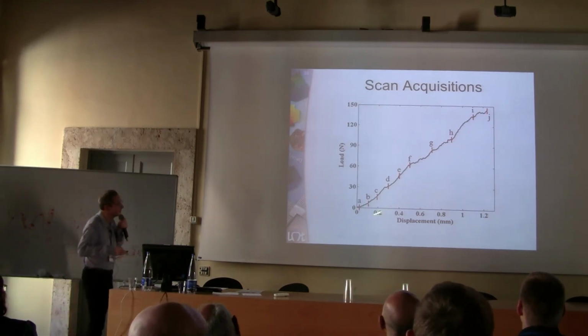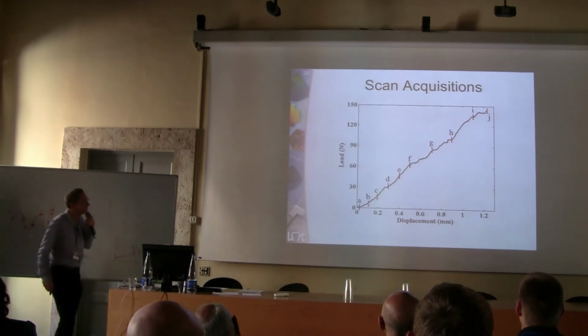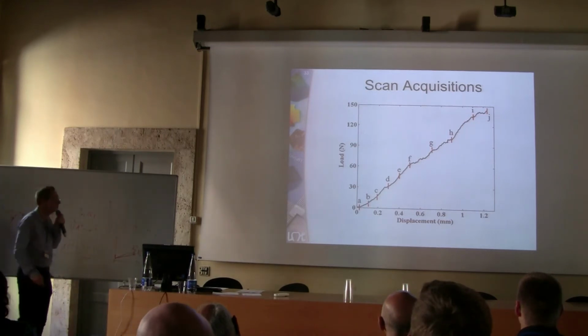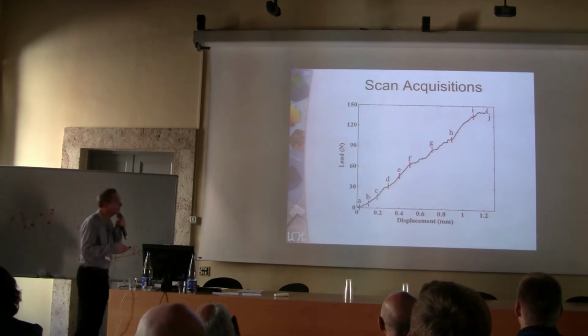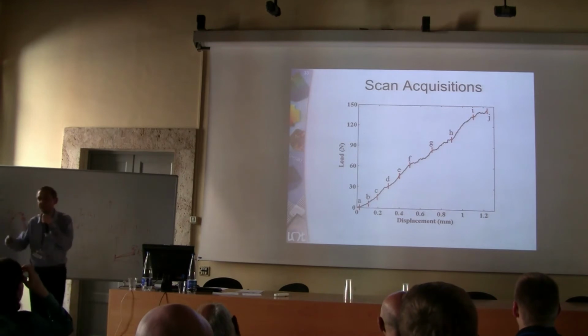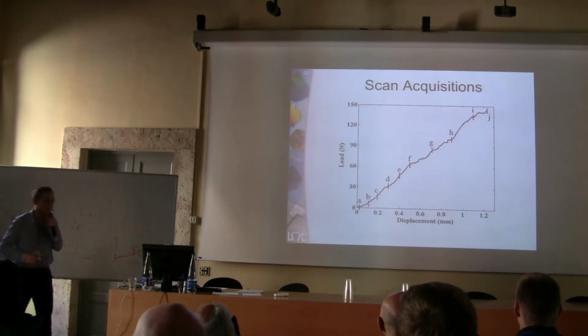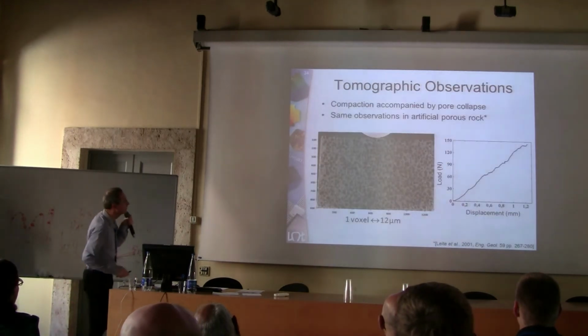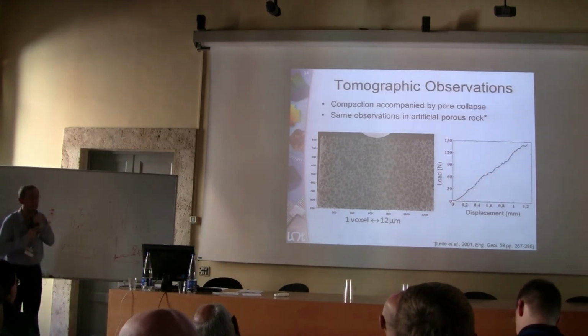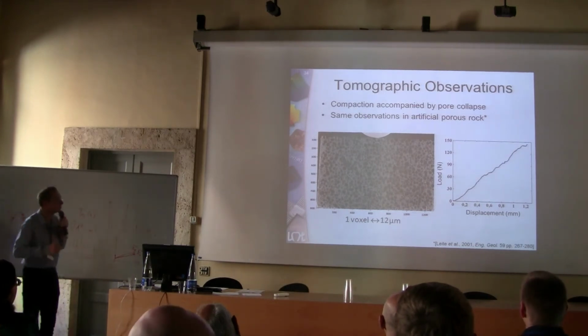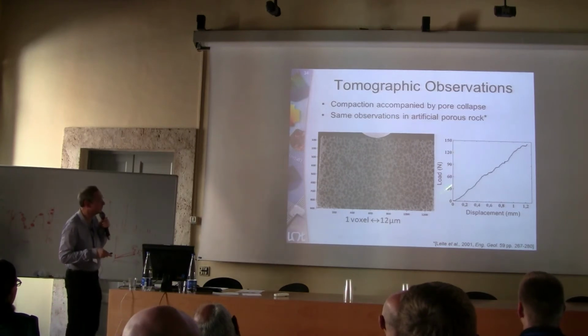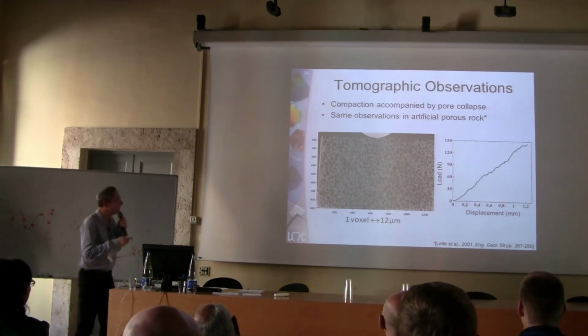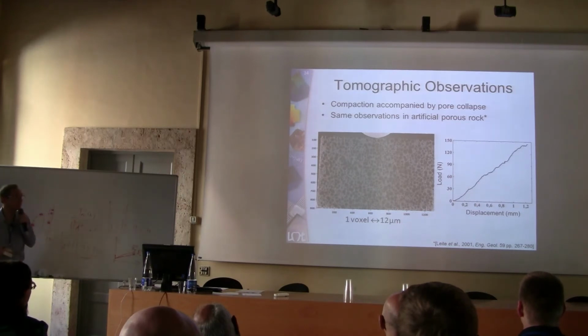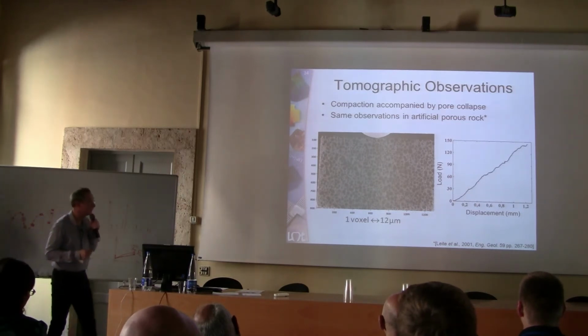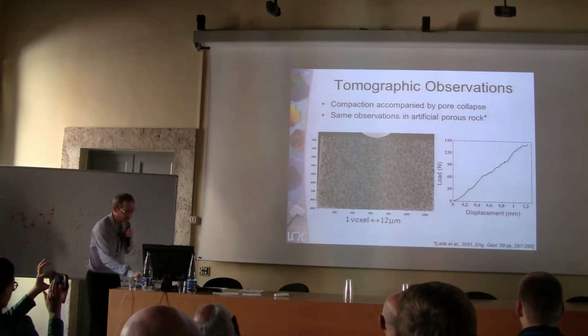In this experiment, here you have the load versus displacement curve of the indenter, and the fact that this curve is not linear is an indication of a nonlinear underlying mechanism. Each letter here indicates that you are acquiring one scan. So here now we'll see the central section of each of these scans as the applied load increases. In this particular case, the experiments were performed in Lyon, at the MATEIS lab, so in a lab tomograph.